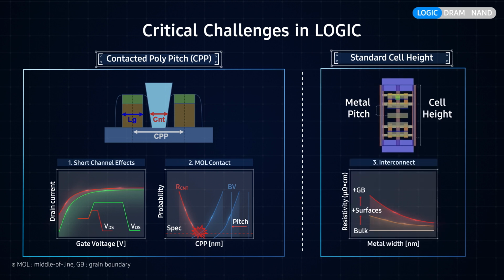In order to scale down CPP, we need to reduce the dimension of either the gate length or the contact. However, decreasing the gate length induces large leakage current due to short channel effect, and decreasing contact dimension induces large contact resistance. On the other hand, in order to scale down standard cell height, we need to reduce metal pitch, therefore metal width. This inevitably increases metal resistivity due to non-trivial surface and grain boundary scattering. Therefore, critical challenges in logic technology are short channel effects and contact resistance. In order to overcome these challenges, now let us look into innovative approaches by focusing on structures and materials.